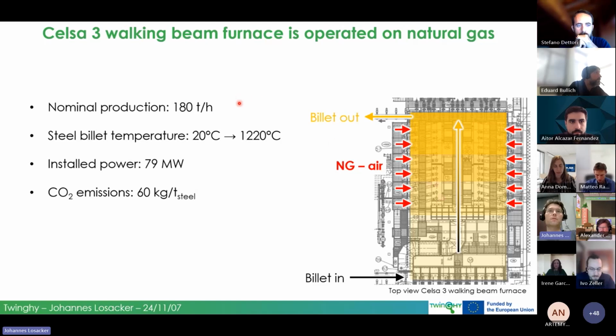To give you some basic figures of the furnace and the process, it has a nominal production rate of 180 tons of steel reheated per hour. It usually runs a bit lower, at about 100 tons per hour. Steel billets enter the furnace at about ambient temperature, usually about 20 degrees Celsius, but sometimes, as these billets come straight from the caster, they might not have been cooled down entirely and can have temperatures of 300 or up to 400 degrees Celsius. They are loaded into the furnace and heated up to about 1,200, 1,220 degrees Celsius for hot rolling. This is done with an installed power of 79 megawatts of natural gas, and this results in specific CO2 emissions of about 60 kilograms per ton of steel reheated.